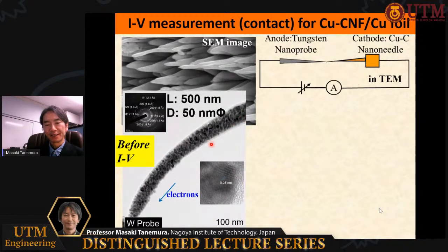This is a TEM image before applying the voltage. Black dots disperse in the carbon nanofibers. Those black dots are copper nanoparticles. We can observe copper lattice like this.